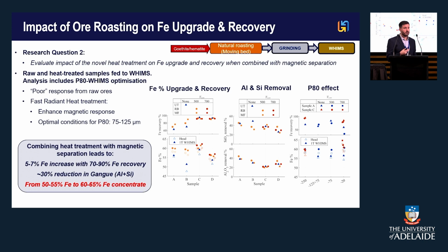The second research question is: can we upgrade the ore? And if yes, by how much? This really depends on the initial mineralogy, but on average, the fast heating high flux radiation method was able to provide an upgrade of roughly 7% Fe units with very good iron recovery. We never had iron recovery, at least at lab scale, of less than 80%.